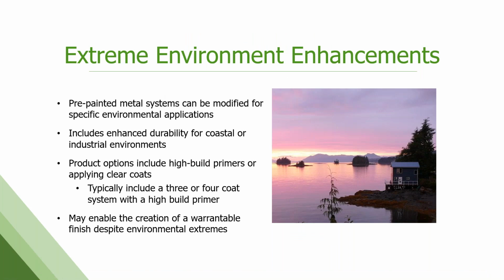Extreme environmental enhancements. We can modify these to get some warranty and performance. The biggest one is marine or coastal locations. Again, typically you're going to use a high build primer. So instead of the typical primer that's about 0.2 mils of film, you're going to go to a 0.8 or a 1 mil thickness of primer. It's going to give you extra corrosion protection. You may also need a clear coat in addition to that, just to hold up in that environment. So these are usually 3 or 4 coat systems. Has to go back through the paint line more than once to get all that paint applied to it. So there's some cost there, but you can get a warrantable product doing this.